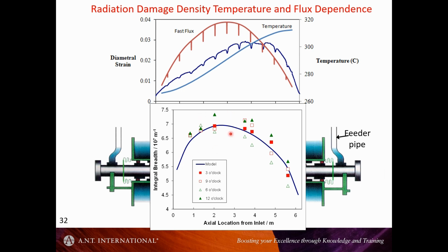And at the cooler end, you tend to get a higher density of radiation damage and a lower density at the hotter end. These values here for the damage density are taken at different clock positions, starting at 6 o'clock, which is at the bottom here, and 12 o'clock at the top. And what that basically means is, as you go from one end of the tube to the other, the spread in the conditions around the tube increases, and the tube gets cooler at the top and hotter at the bottom, and that's reflected in the damage density.